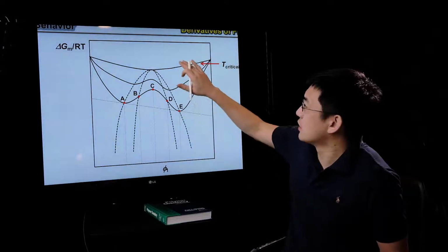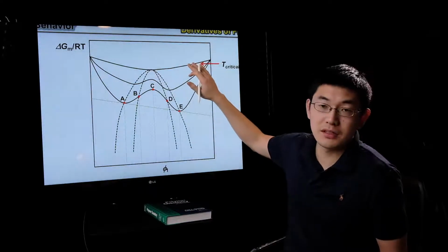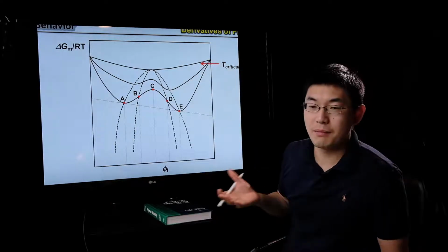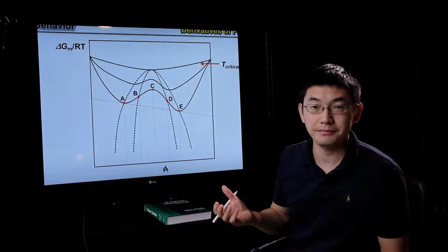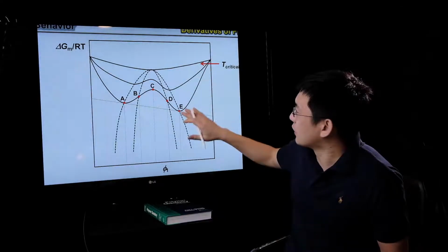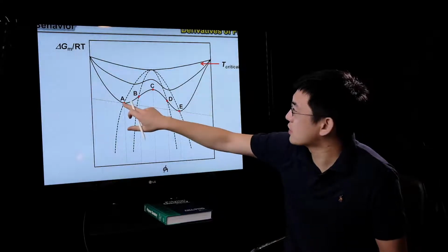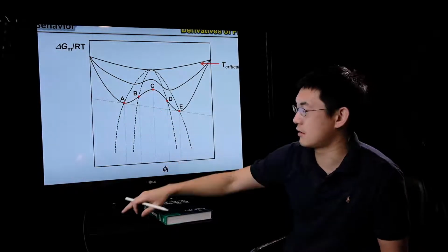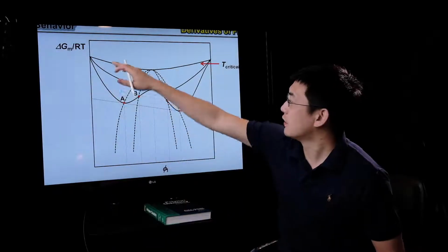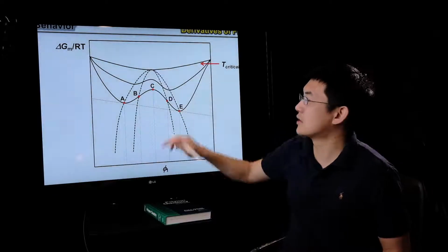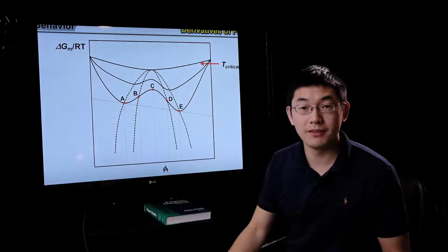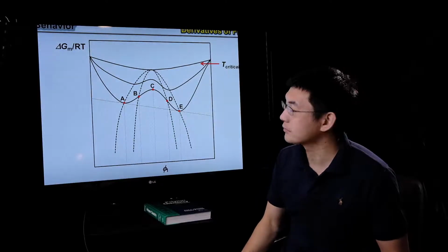And this is what you see in the 3 curves. And we kind of discussed it as well in the last lecture. Depending on the magnitude of the entropy, you would have these local bumps come into play, and these local bumps will result in instability of your sample. If delta G is always concave up, then you're always going to mix, and this will be the one phase, a very simple problem.